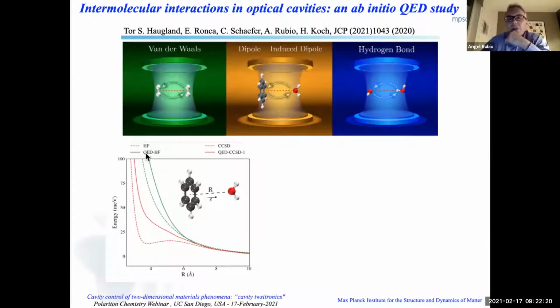Then if you take Hartree-Fock and many density functionals, you will get that the system is in most cases unbound. In the gas phase, you get the solution in the coupled cluster singles and doubles, which is this small dip, which tells you that the water molecule is bound with the benzene molecule at a distance of around 4 angstroms. However, once you put this molecule in the cavity and the cavity is tuned to the HOMO-LUMO excitation, you immediately see that this bound state is being removed.